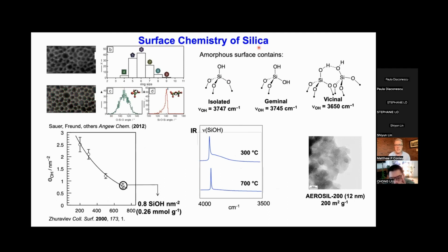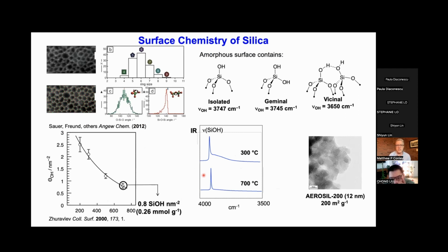And I start with silica because silica pops up a few times on this slide. In the surface organometallic world, silica is really sort of the workhorse ligand. So instead of thinking about the complexities of silica, because silica is an amorphous material, very difficult to come up with accurate models that reflect the coordination environment of silica or the material properties of silica, we can use that similar reductionist mentality that Tolman taught us to just think about, what's on the surface, okay? Because inevitably, whatever we add to silica or any oxide is going to be bound to the surface selectively, okay? So silica surfaces, though they are extremely complex, we can simplify them quite quickly.